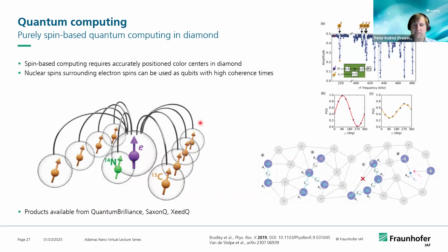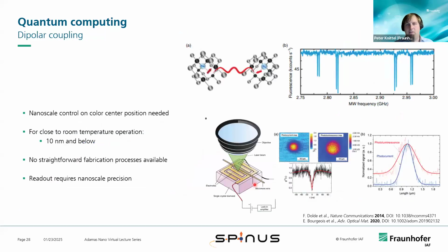The problem is that obviously the system is hard to scale. In principle, there are two approaches studied at the moment to scale this system. What you want is that in some way the signal from the NV center is coupled to another NV center. And how can you do that? You can go with dipolar coupling. So you place the NV centers in very close proximity so that they see each other. This was already demonstrated, but you could imagine that placing these in close proximity, which means in a range of 10 nanometers, is technologically very difficult, and it's not something that is straightforward. But people are working on that.